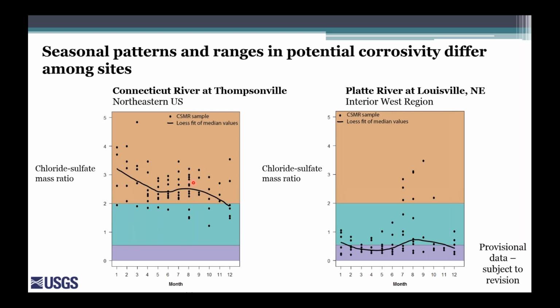It can also be the case that because of the prolonged use of road salt in that particular basin, you're actually getting a contamination of groundwater with road salt. And this has been demonstrated in a few areas in the northern parts of the country that have had a long-term usage of road salt. But in any case, the pattern that we see in the Connecticut River is consistent with the idea that road salt really drives these high winter values. And the second thing I'll point out about this is that all of the values in the Connecticut River are quite high. As I mentioned before, when the chloride to sulfate mass ratio is above 2, it indicates a high potential to cause corrosion in a water distribution system, and the majority of the observations are above 2 in this particular basin.